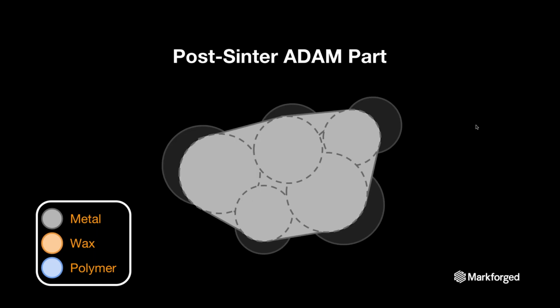So post-sinter, that part shrinks down roughly 17%. Our software accounts for that shrinkage depending on what material you choose, whether it be 17-4, which is what we have right now, to H13 that's coming out very soon, the A2, the D2, Titanium 6-4, Inconel 625. All those that are coming online will be able to be printed by the same printer, washed in the same wash, and sintered in the same oven.